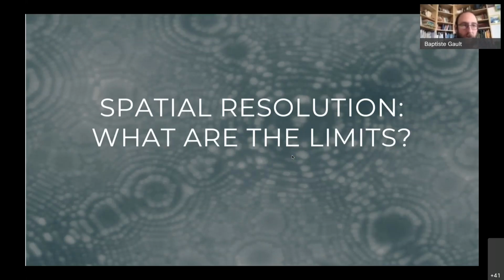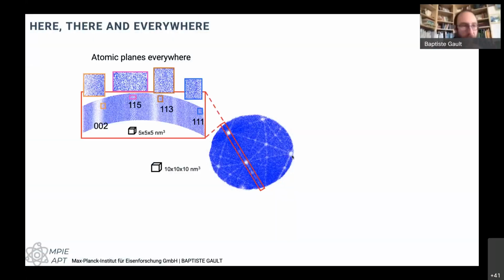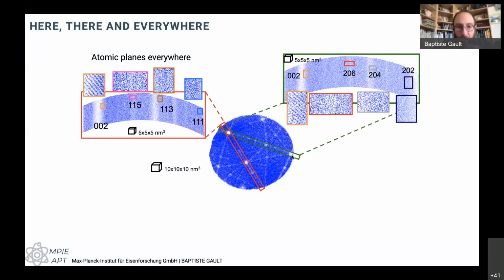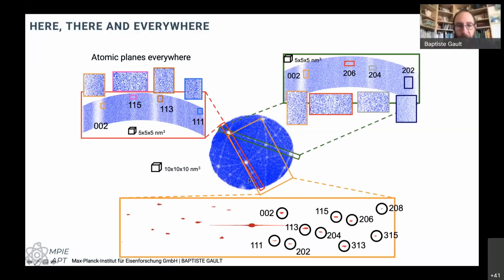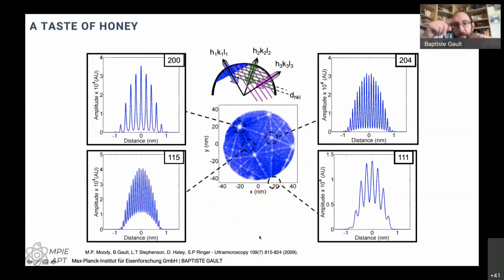So again, if I look at some of these data sets, I can see a lot of atomic planes across this tomographic reconstruction that I've built. I can do a Fourier transform, for example, to see that effectively there are planes, and there is almost like a diffraction pattern that we can form based on the spacing of these planes. We'll have a series of spots that form in the reciprocal space. I can also use other tools to look at the average distance between atoms going straight down this set of planes here, or that one, and I can measure the distance between planes.